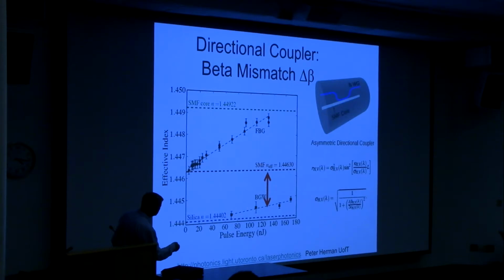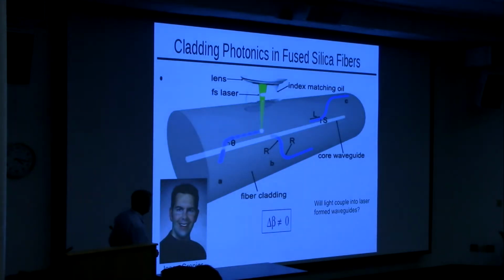So we have this difference, and if we were to look at the theory, this is called beta mismatch, and so the coupling coefficient is dramatically reduced based on these differences. The only way to counter that is to increase the coupling coefficient. So if you make the waveguides closer that you form, then this K value gets really big, and then you can get strong coupling approaching maybe 90% or so. So there is some optical engineering that is really important.